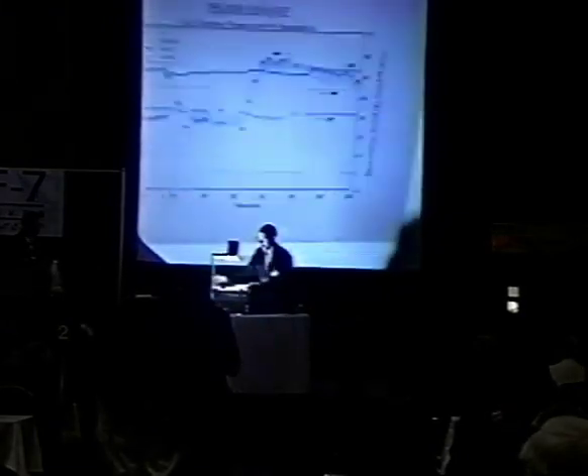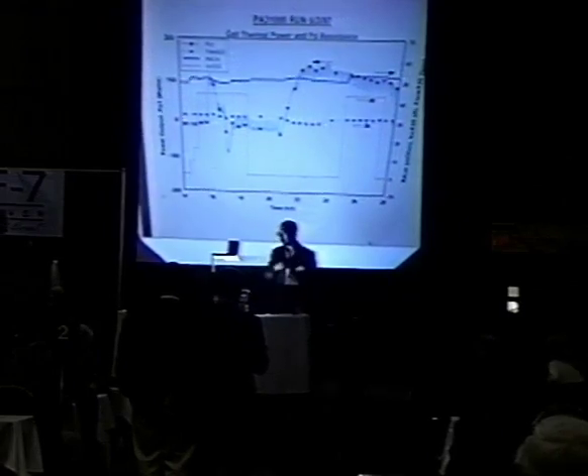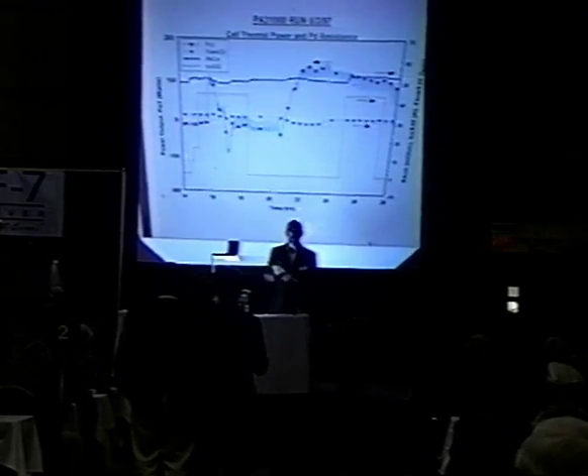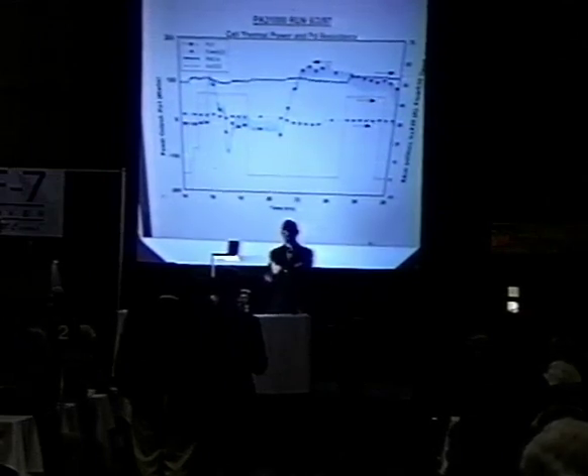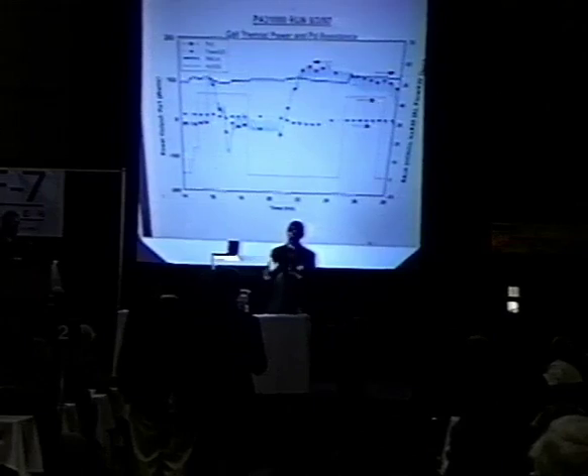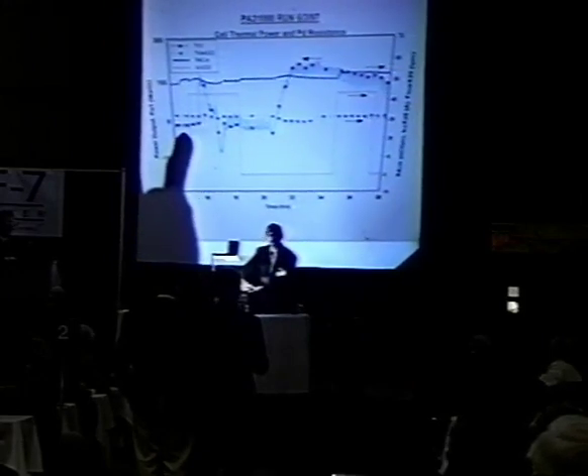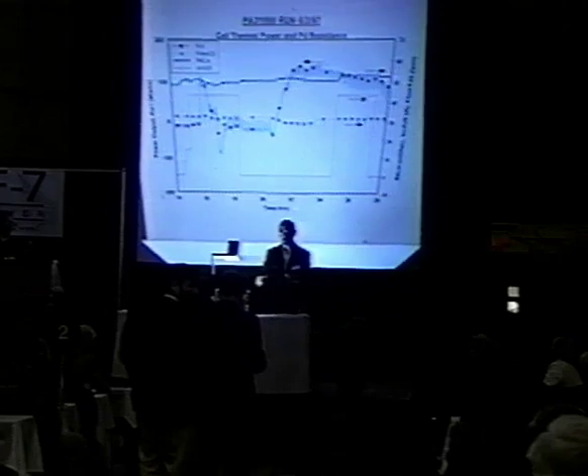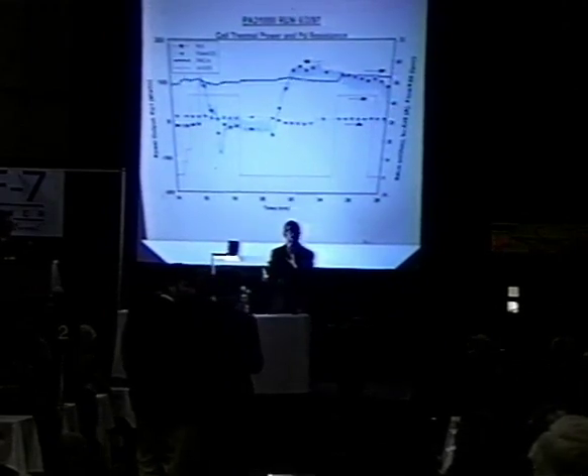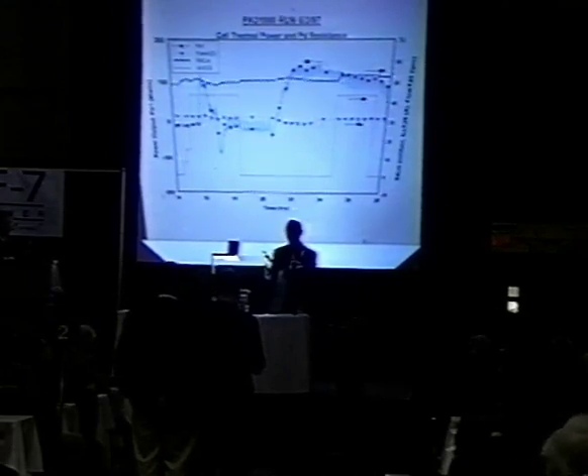Right. Yeah, that's a very good point. In fact, this is right here, the reason why the power is negative. If you take a look right through here, typically what I do is keep track, all this power indication is the flow rate times the delta T of the calorimeter. If the inlet is hotter than the outlet, that means we're putting power into the cell, and so that power calculation is going to be a negative number. Whereas if the outlet is hotter than the inlet, it switches. It typically takes several watts just to keep this cell warm. In other words, when you heat the thing up to 60 degrees C, you still have to keep putting power into it just to keep it at temperature. And that's where that negative number is coming from.